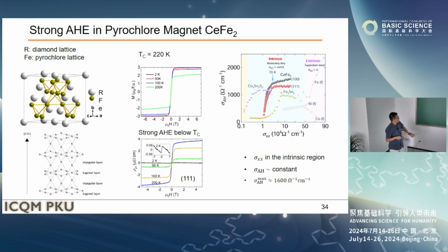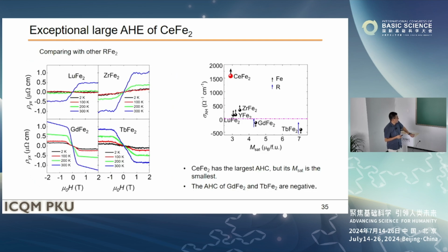For cerium iron 2, we measured the magnetization and see it's a ferromagnetic compound with TC around 220 Kelvin. And we also see a very strong anomalous Hall effect in this compound. This anomalous Hall conductivity is very large, larger than other compounds as far as we know. So why is it so large? We can compare with other compounds. You find something interesting. We compare with non-4f compounds, like lutetium and zirconium, which have no 4f moment. And we also compare with 4f local moment compounds, like gadolinium and terbium.